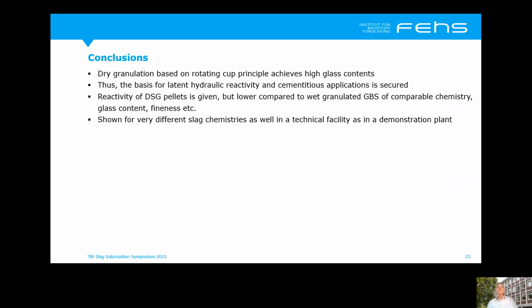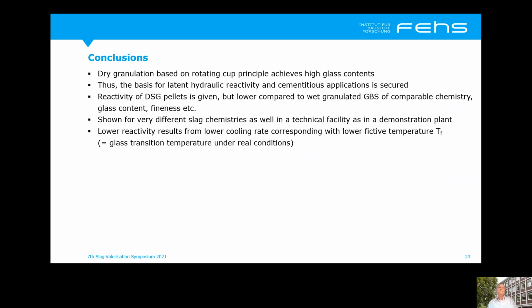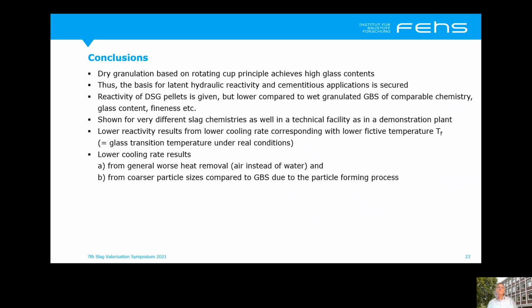We could show that for very different slag chemistries, as well in a technical facility as in a demonstration plant. In a technical facility, we had different chemistries and much more different compared to the chemistry in the demonstration plant, but the same effect. And the lower reactivity results from the lower cooling rate corresponding with the lower fictive temperature TF. And the lower cooling rate results as well from the generally worse heat removal by air instead of water and from coarser particle sizes compared to GBS due to the particle forming process in the dry granulation process.